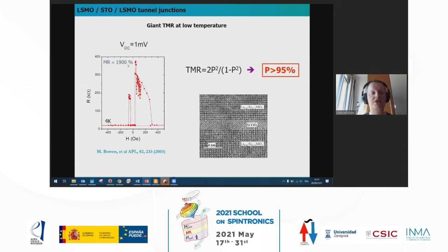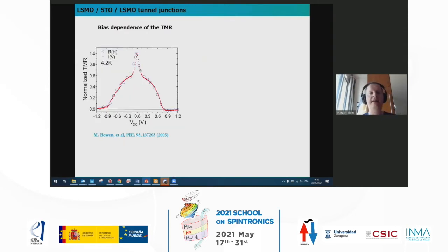And here we could measure a very high TMR of almost 2000%. So this was more than 1 order of magnitude higher than any TMR measured at the time. And so it was really qualifying these manganites as very interesting materials for spintronics. And you can calculate the spin polarization from the TMR, and we got something in excess of 95%. So really very high. So these manganites can be used as almost perfect sources and detectors of spin currents. And you can use that to gain insight into the electronic structure of materials, for instance.